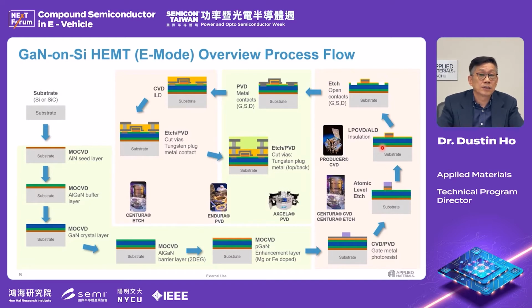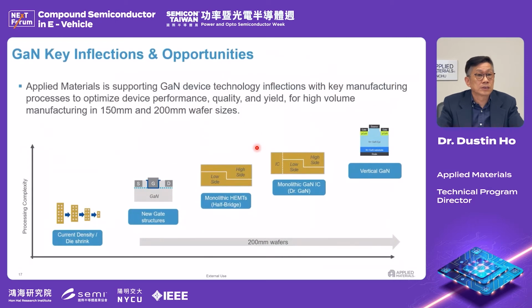Then ALD or LPCVD for the silicon nitride insulation to protect the AlGaN area. Then you need another etch for the open contact for the source and drain. Then PVD metallization, and then PECVD for ILD. Then another etch and PVD for the metallization. And sometimes for the backside you can have the backside part. So we offer most of the process tools for this process.